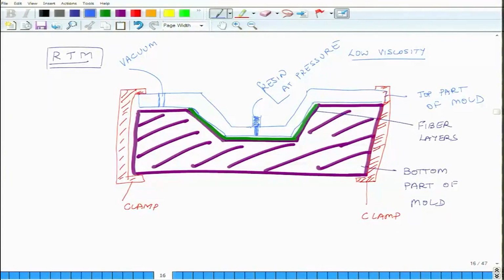It wets everything, and of course, this is assisted, there is also a vacuum to remove all the air, and once it has wetted everything, then you apply heat and you do not apply a lot of pressure, and in that state you let it cure. So, as a consequence, you get a high quality, high finish product. Of course, finish is on top side and bottom side with low porosity, and also the fibers are not disoriented more than what can be tolerated. So, this is all about RTM.